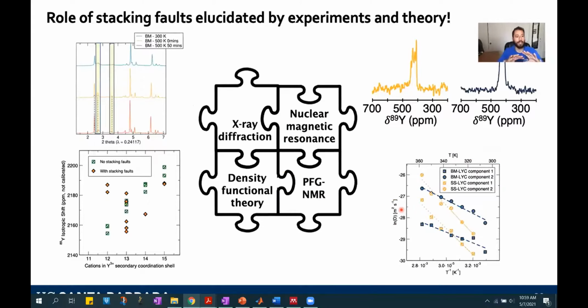So I can piece together all these different little pieces of the puzzle. I saw from my X-ray diffraction that I had stacking faults. I used NMR to confirm it by looking at the different synthesis techniques. And then I gained an understanding of what my NMR spectrum and conductive properties would be from density functional theory calculations. And finally, I confirmed that in my material with stacking faults, we get easier conduction. And all of this was done by putting together a lot of different characterization techniques to get a full picture of the material.